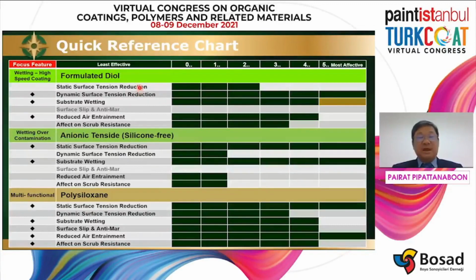If you get formulated diol, you are still okay for static surface tension, but you go more to dynamic surface tension reduction that you get for both industrial application or spray application, curtain coating. You get good substrate wetting and also reduced air entrainment, but you don't get surface slip or anti-mar. If you need most of it or all of it, you go to polysiloxane.